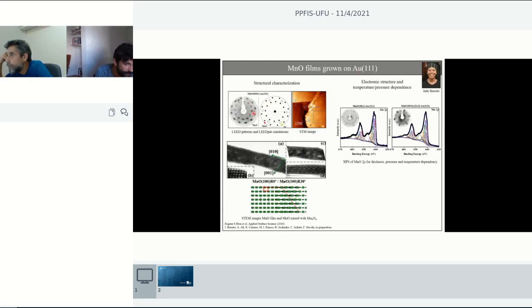So this is the typical LEED pattern that we obtain, where we analyze the position of these diffraction spots and the distance between them with respect to the underneath substrate, that you can see basically here, very faintly. We can judge what's the position of this oxide on top of gold, and then judge about the structure of this oxide. To add to this kind of characterization, usually we perform STM imaging. It means that we use the scanning tunneling microscope, where everything that is bright here is where you have more electrons. Usually we can assign this to the position of the atoms. And then we can recognize some of the structure that we identified here in the diffraction pattern. That is this square pattern over here.